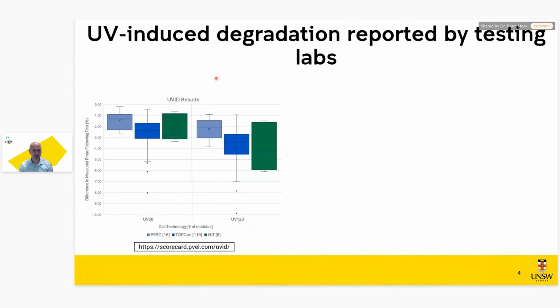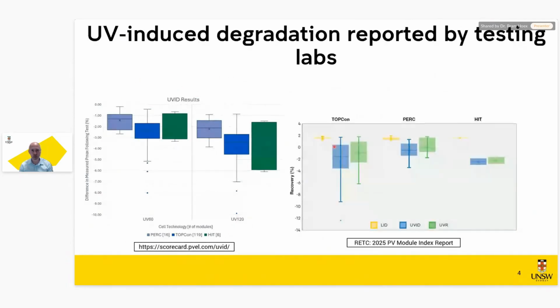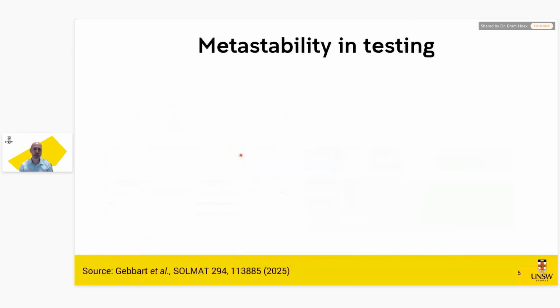It is also confirmed by testing labs, PVEL and RETC, where we see, particularly for TOPCon, an average reduction, but also some outliers that show even 10%. So there's really a high variability, and that's an indication that the problem is not yet fully understood. So we still have a way to go to bring it up to acceptable levels.